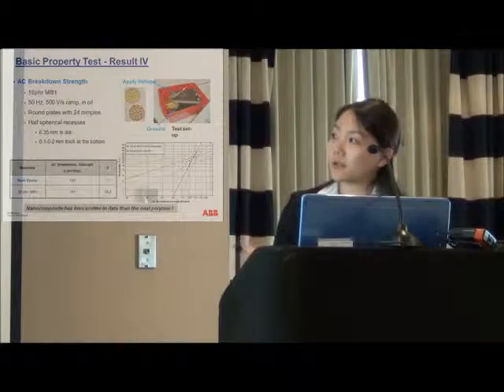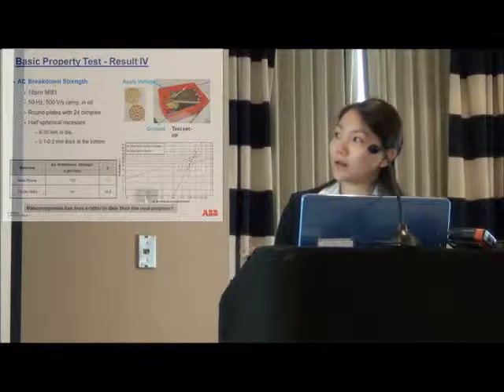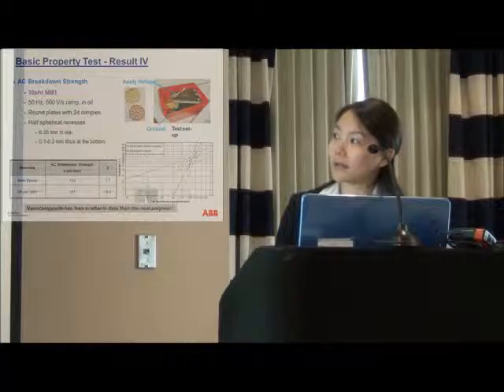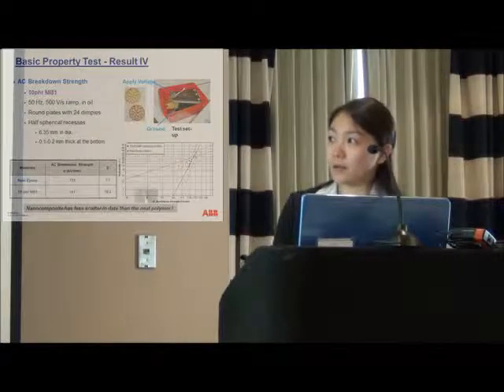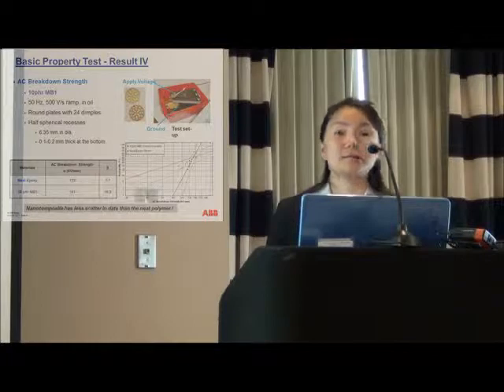This is a Weibull curve of these two materials. The red one is the neat resin and the black one is master batch 1. The AC breakdown strength, the alpha value, is very similar for both.